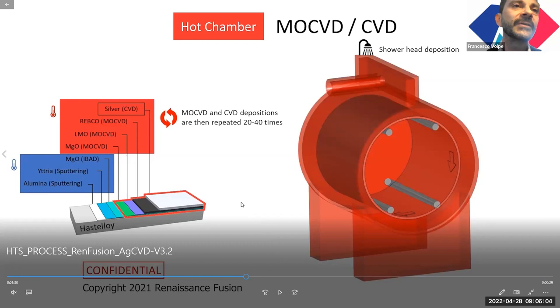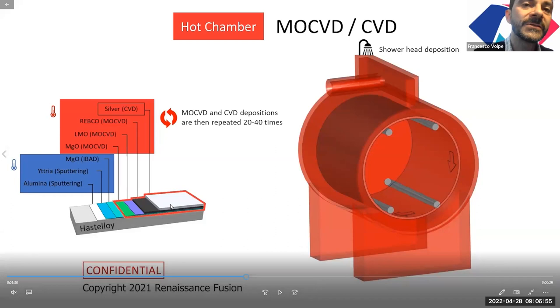Okay, so that sequence in the red enclosure on the left. You see some layers in a blue box in the cartoon on the left, and some layers in a red box. The layers in the blue box are sputtered and ion beam assisted deposited in a cold machine. The layers in the red box are deposited in this hot machine that Chris is showing now. The red sequence is repeated over and over between 20 and 40 times. And what prevents delamination is the fact that the last layer of sequence N is epitaxially grown by chemical vapor deposition and serves as a good substrate to initiate the sequence N plus one.